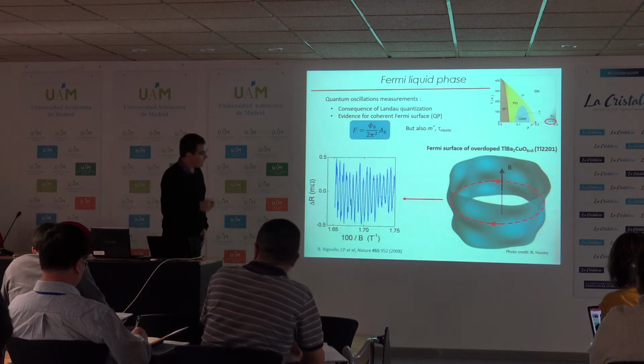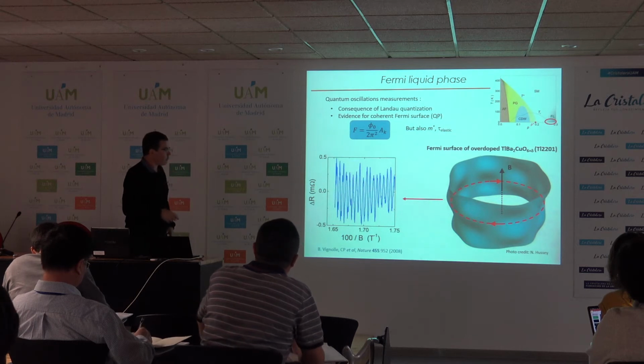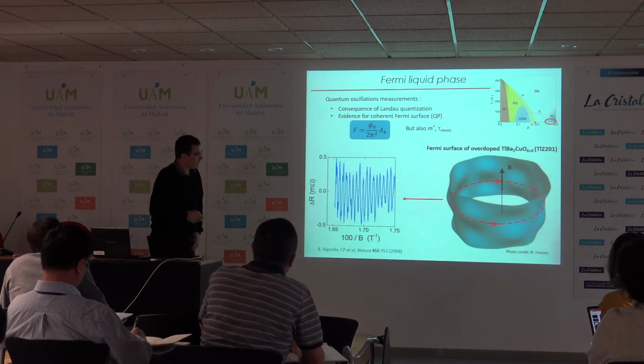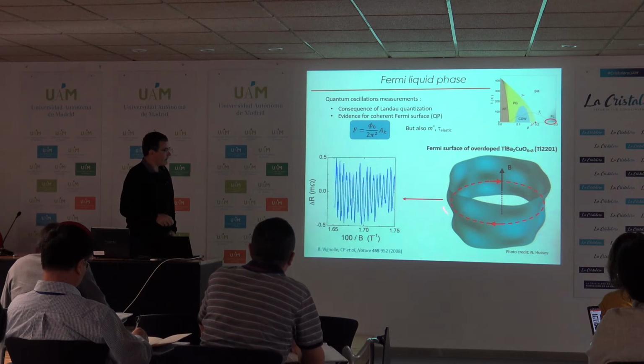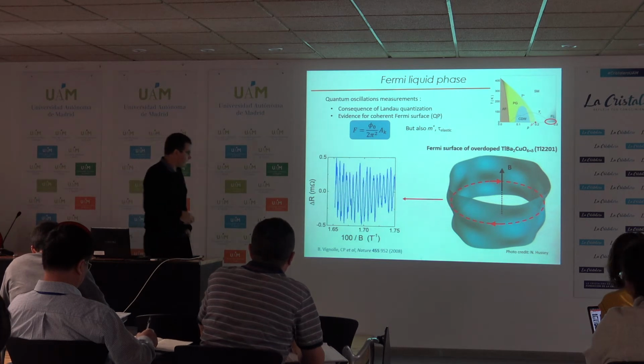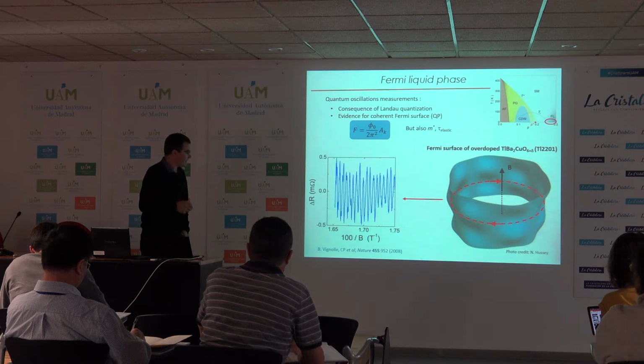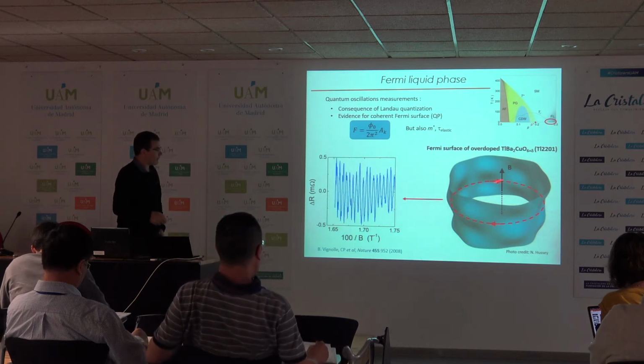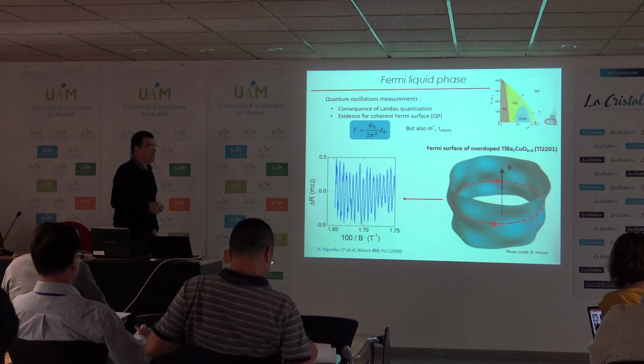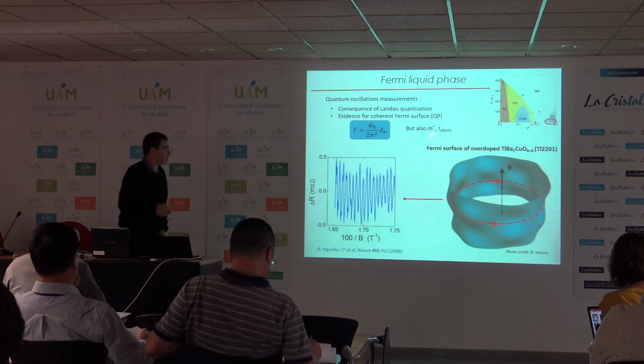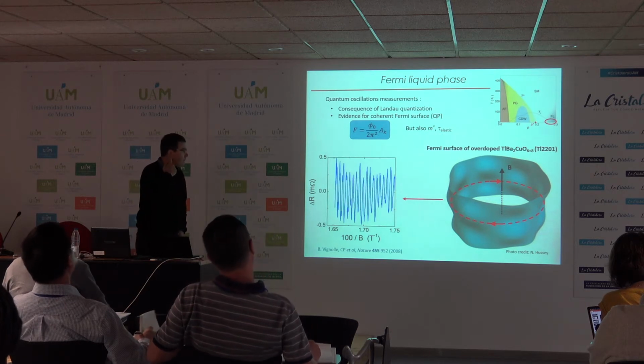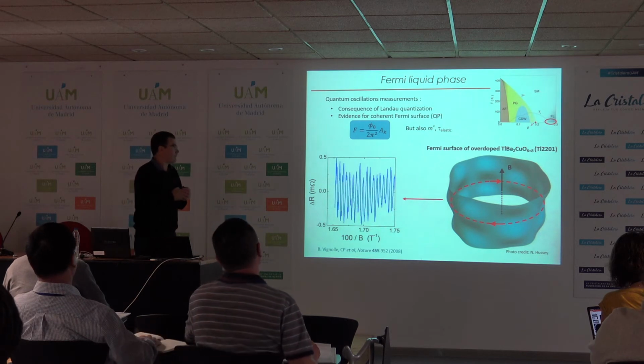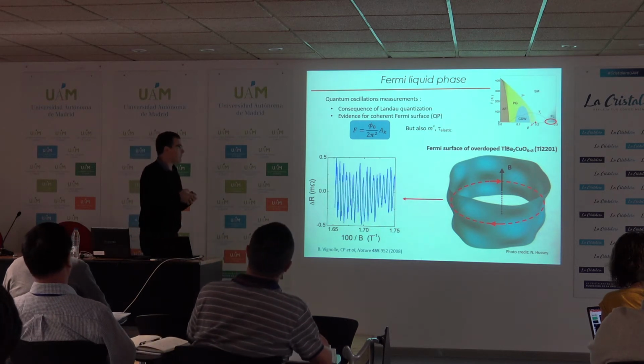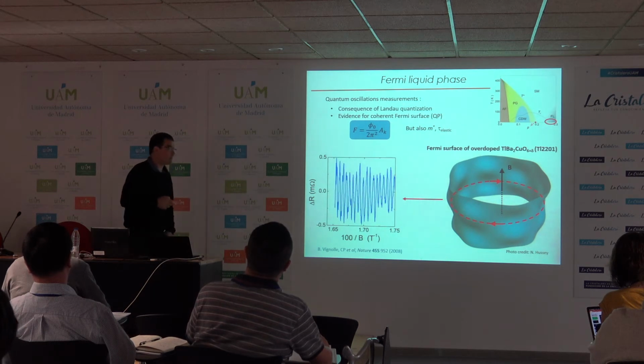Here I show a cartoon of the Fermi surface of thallium-2201, where the warping has been exaggerated, but basically if you put a magnetic field along the axis of this 2D cylinder, the electron can make a cyclotron orbit like this, and some quantity like the resistivity or the magnetization oscillates with a frequency which is proportional to this area here. This measurement can also give you information about the effective mass, through the analysis of the temperature dependence of the amplitude of the oscillation, and the Dingle temperature, which is related to the elastic scattering rate.